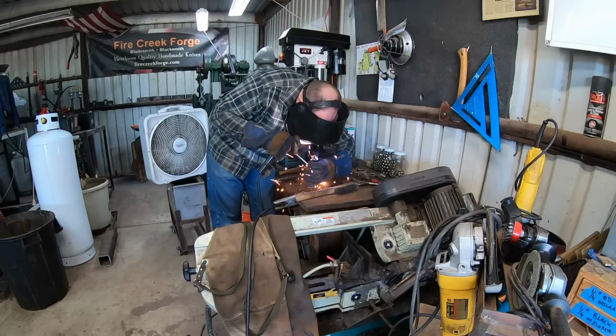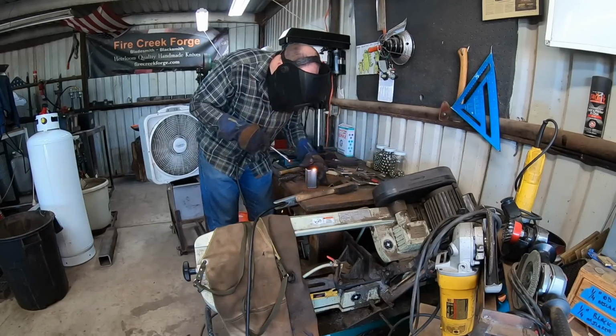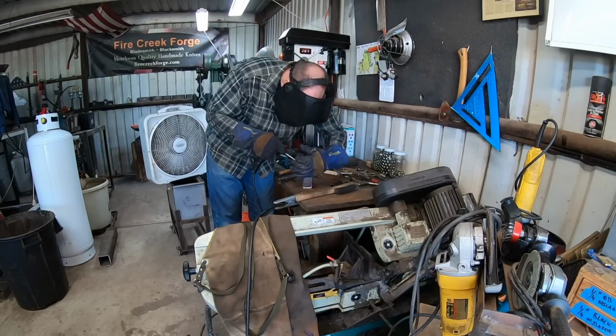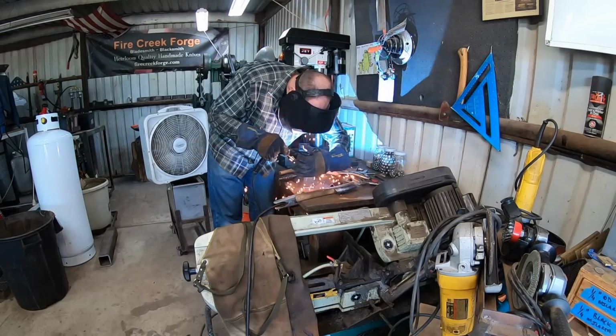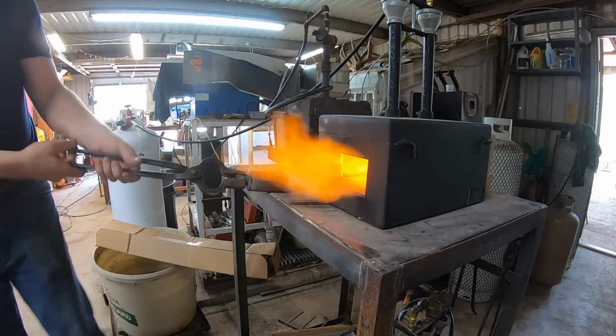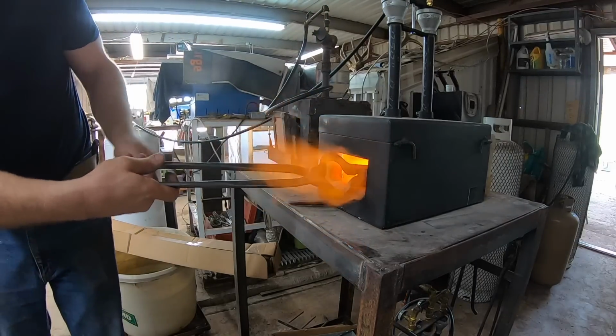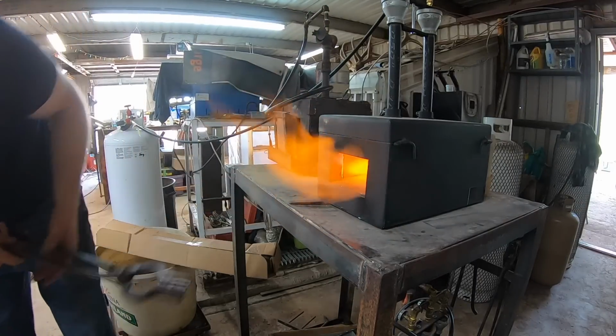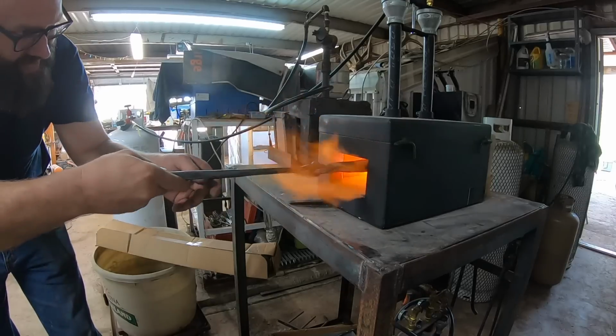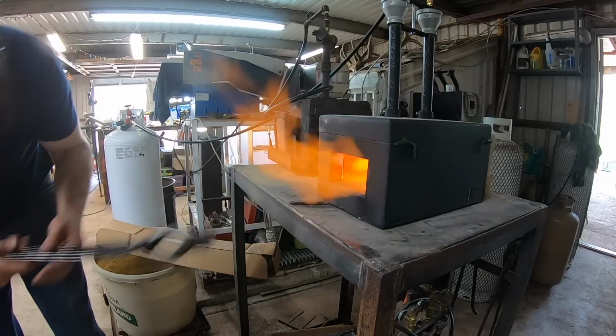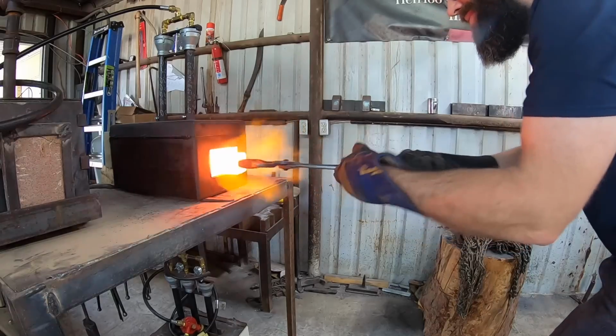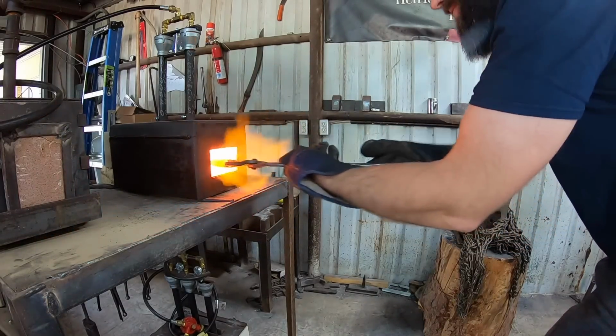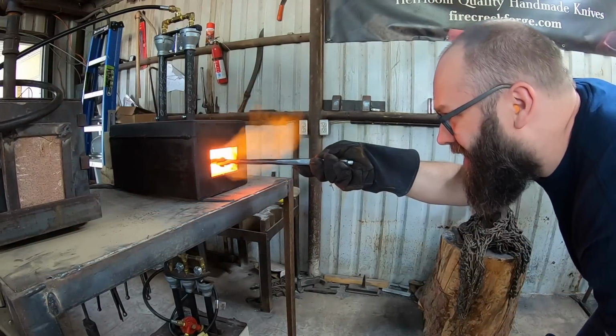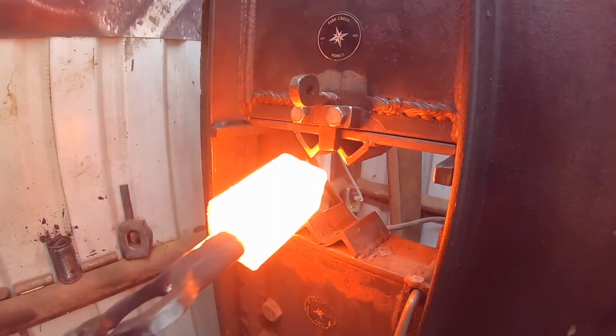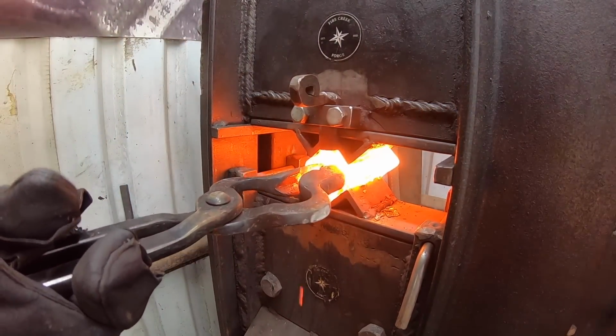Once that's complete, I can weld the other end cap on for a nice clean can. I will note that you do need some kind of a vent hole, so while I'm welding that last cap on, I will make sure that the little pinhole presents itself and you can see it kind of off-gassing. With my arc welding that's not so hard to do, but if you weld stuff airtight you do need to drill a tiny hole in the canister somewhere.